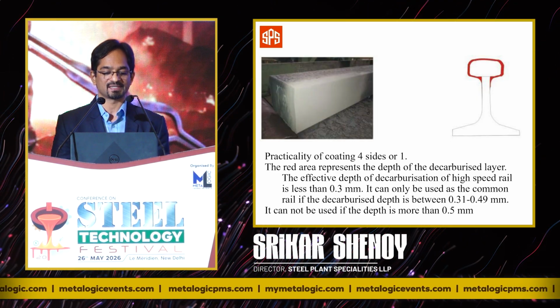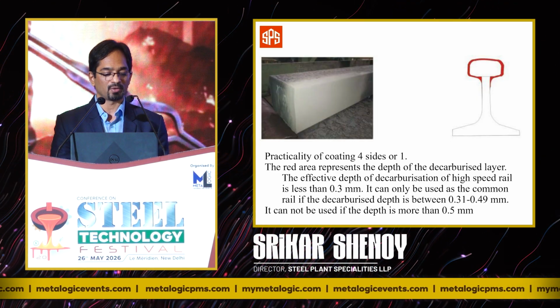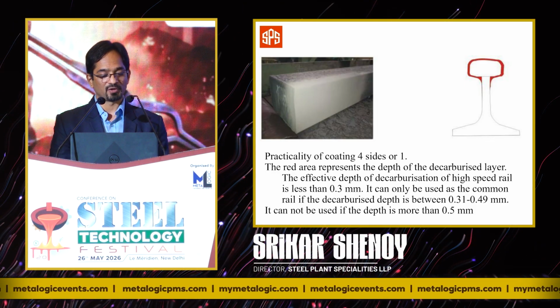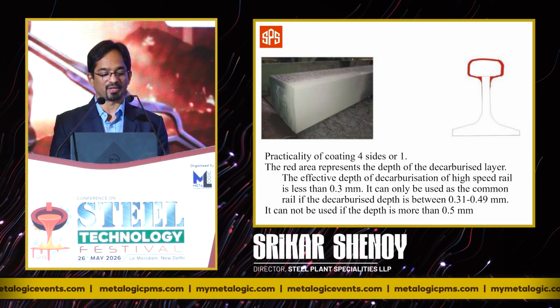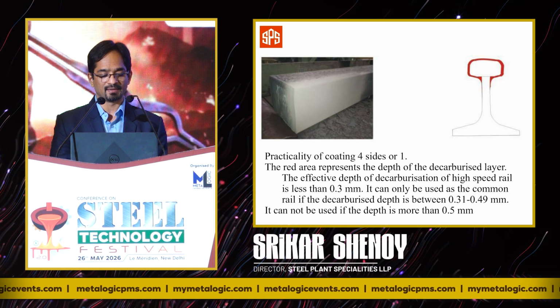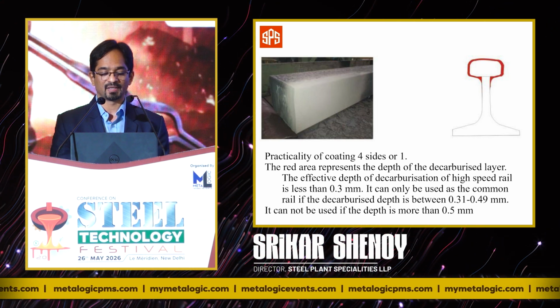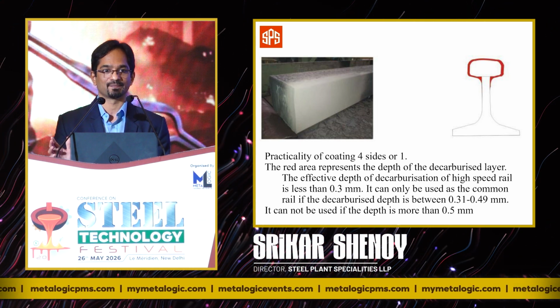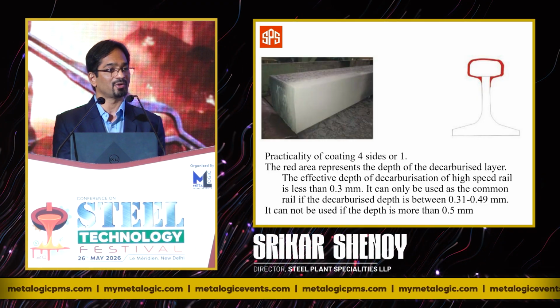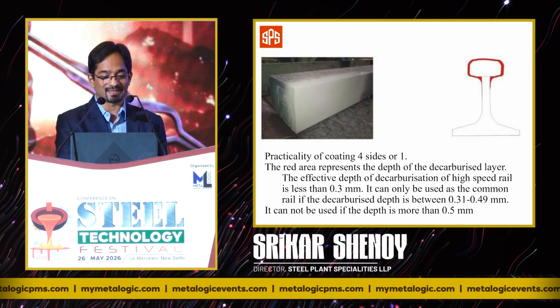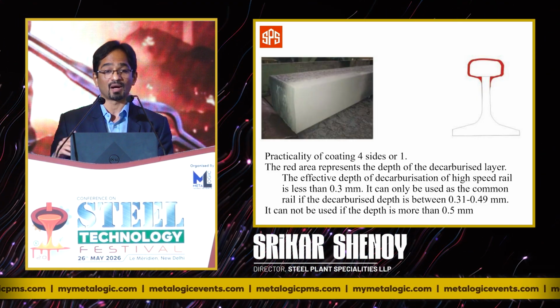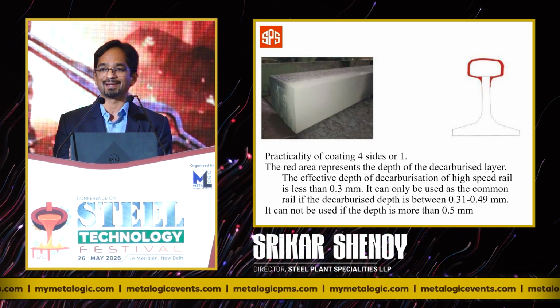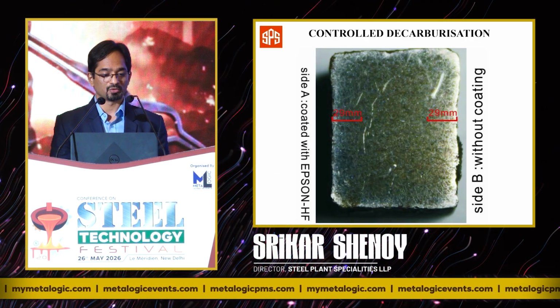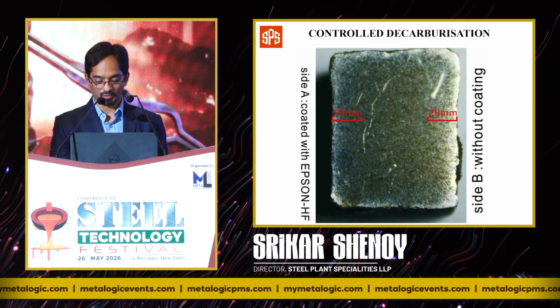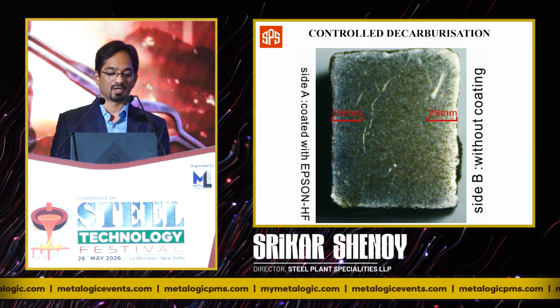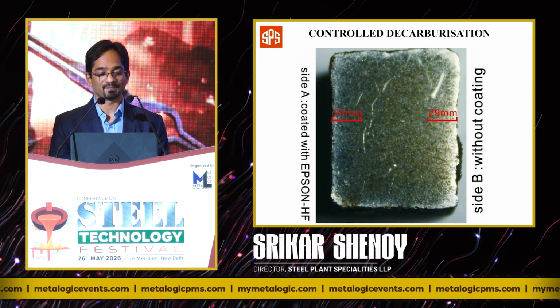Decarburization is a surface deterioration phenomenon. We need to control it, and if your depth of decarburization is less than 0.3 mm, it can be used as rail steel. If it's more than 0.5 mm, it cannot be used as rail steel. It's straight away a rejection. So imagine you're heating your billets with the intention of making rail steel, and your decarburization is above 0.5 mm, you are losing the entire heat. So to control the decarb, here is the coating that is applied, and a quick cross-section view of the result.